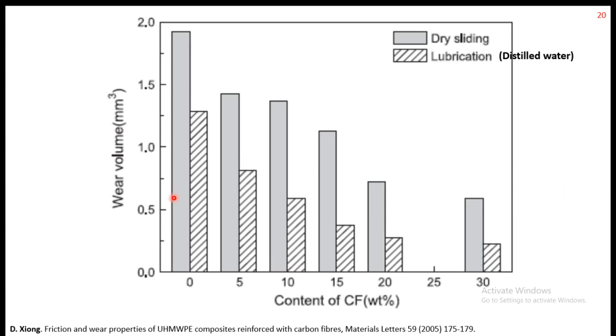Even in the wear rate, we found that with lubrication the wear rate actually goes down. This is carbon fiber percentage by weight: 5%, 10%, 15%, 20% and 30%. As we increase the carbon fiber weight percentage, the wear volume goes down compared to pure UHMWPE. This is quite encouraging, especially for the lubrication case. But as I said, this was done in distilled water, so we need to evaluate it in bovine serum and see whether we get the same result.